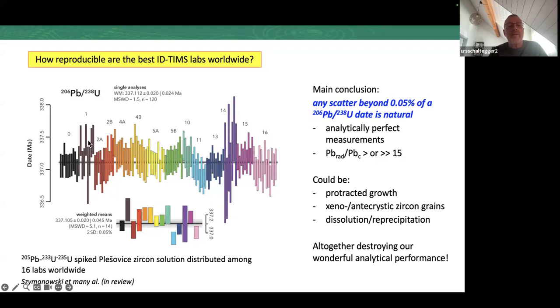But of course, don't forget, these are analytically perfect measurements at very high radiogenic to common ratios, and natural zircons are sometimes much less ideal. Natural causes could be protracted growth, anticrystic or xenocrystic contributions, or also dissolution-precipitation, which are rendering our grain younger. So our wonderful analytical performance gets, of course, destroyed by these natural complexities.